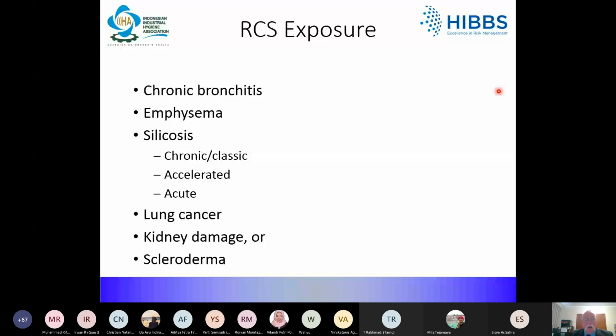Silicosis is classified into 3 types. So you could get chronic or classic silicosis, accelerated silicosis, or acute silicosis. Now, chronic or classic silicosis occurs following long-term exposure to relatively low levels of respirable crystalline silica. The symptoms associated with chronic silicosis may or may not be obvious, and therefore workers need to have a chest X-ray to determine if there is or has been lung damage. As the disease progresses, however, the worker may experience shortness of breath upon exertion and then end up with the clinical signs of poor oxygen CO2 exchange in the latter stages. In the latter stages, the worker may experience fatigue, shortness of breath, chest pain, and ultimately respiratory failure.